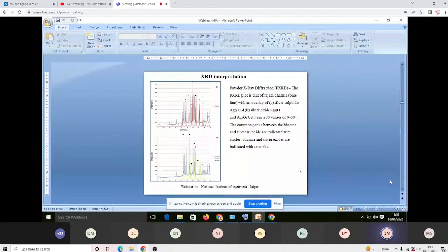So this XRD pattern is the X-ray diffraction pattern of Rajat bhasma, with standards of silver sulfide and silver oxide, Ag2O3. The common peaks between the bhasma and silver sulfide are indicated, and the bhasma and silver oxide common peaks are indicated with an asterisk. In that way you can develop a database of a particular bhasma.